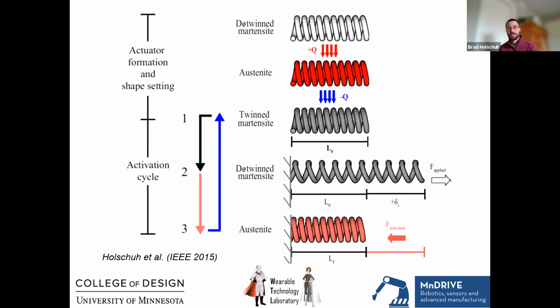And this is what that actuator cycle looks like. You can take some of this wire, nickel titanium wire, off the shelf, wind it into a really, really tight spring, heat treat it so that that tightened shape of the spring becomes its memory state. And then that becomes the form that the material tries to recover to every time you heat it up thereafter. So we form it and we forge it into a spring.